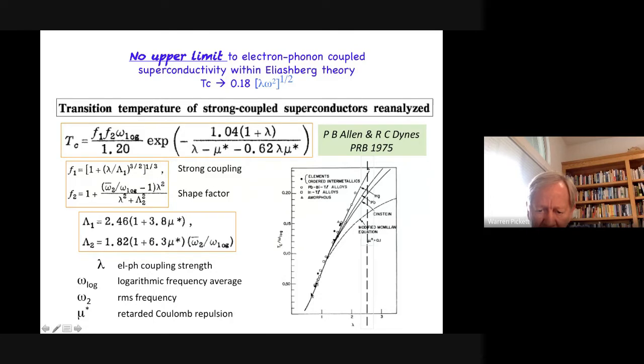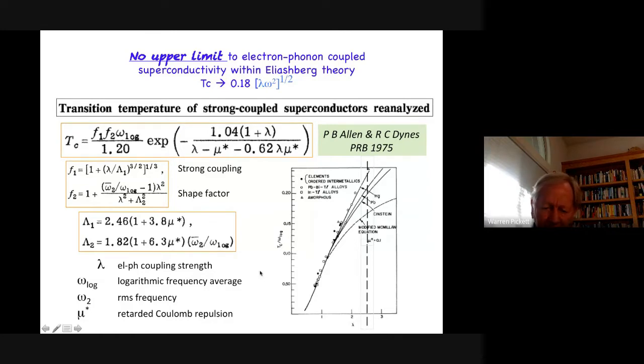And so here is things being plotted versus lambda, and the dominant discussion over the years has been increasing TC by increasing lambda. And I'll show you on the next slide that that is not what's been happening. This is just showing how if you leave out these factors right here, then TC divided by omega log versus lambda increases like it should here, but it goes to an incorrect constant over here. And once you include F1, that doesn't happen. And it actually keeps increasing as the square root of lambda here.